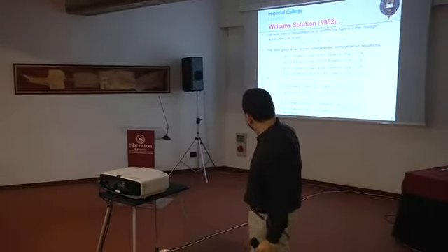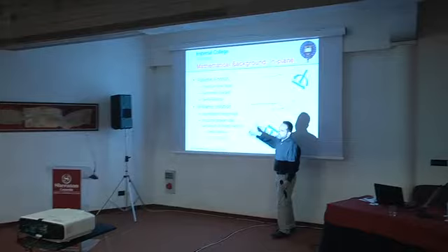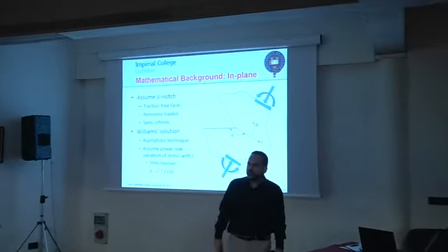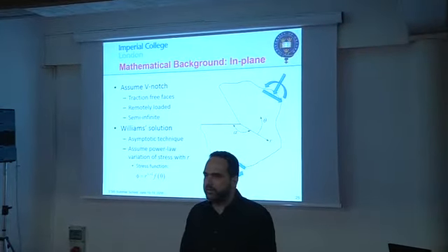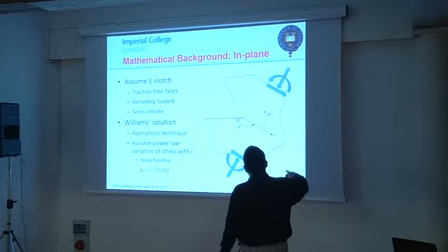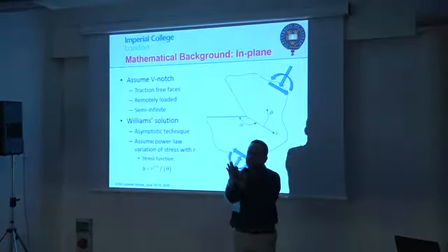Yes. That means that we have an angle beyond which we have an abrupt change, from infinity to 0, of the stress. I was going to get there. So what happens there? I now keep going, opening, opening, opening. Now I open, and my angle, 254 divided by 2 is what? 127 degrees. So I make this angle 127, which means my notch has become fairly big.